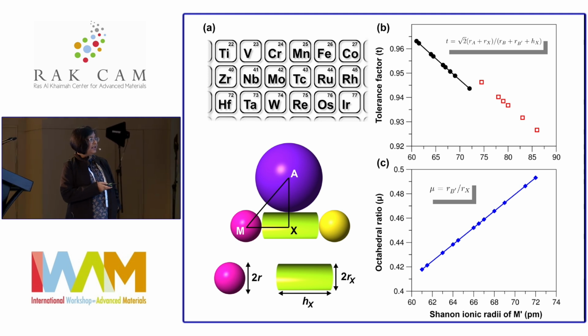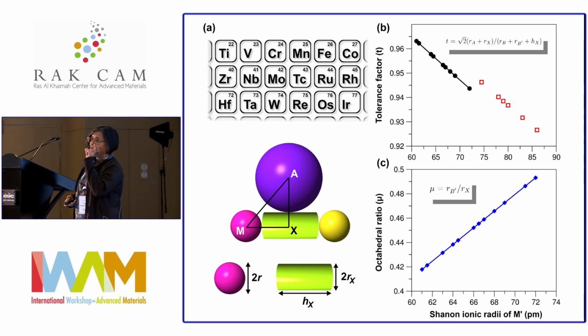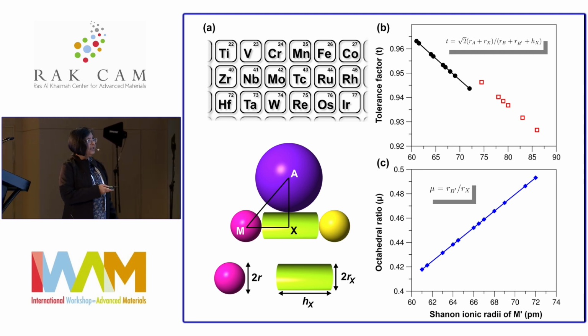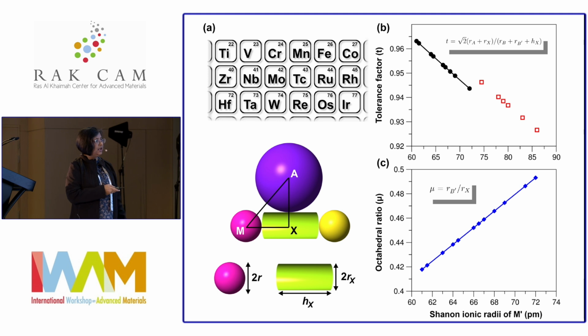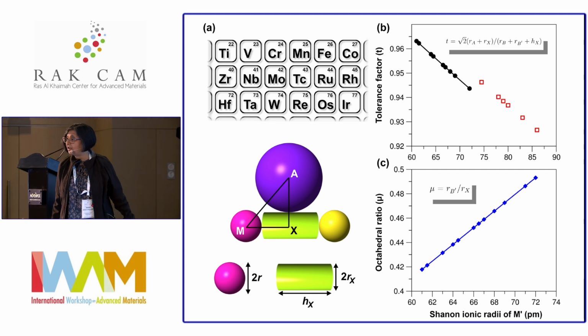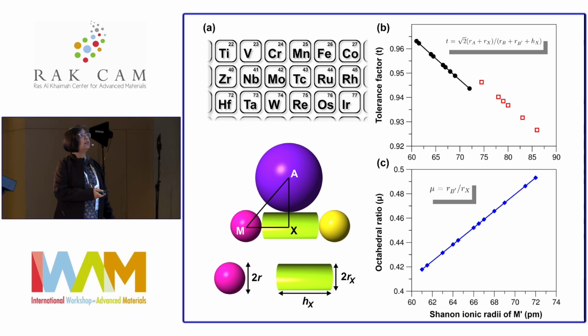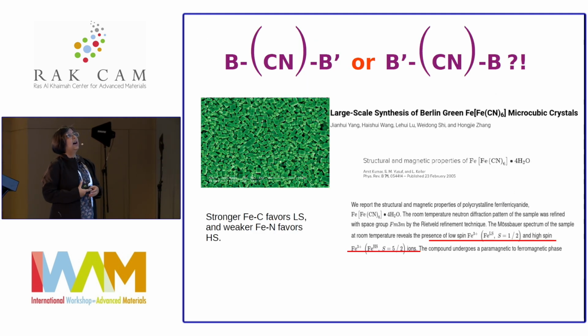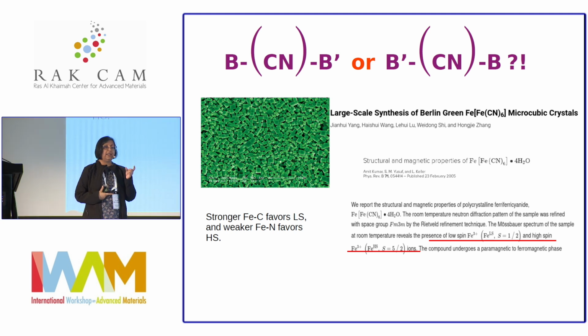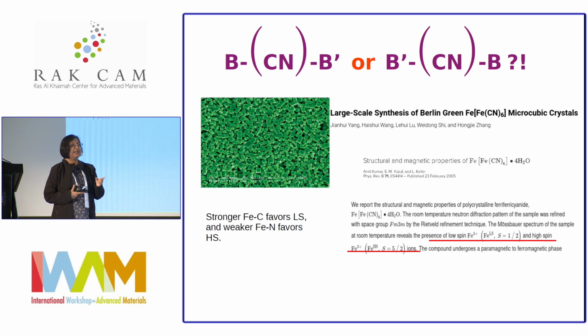So just as a side comment, since you are now considering the polyatomic ligand, which is like a cylinder, when you are calculating the tolerance factor, that's really not the normal way, because you have to introduce the height of it and also the radius of it. And Tony actually worked out all in great detail. So thanks to all this work, we could calculate that. Now, there are two possibilities for which way this CN bond will be. Will it be linked the C to B and N to B prime, or the opposite? In fact, both are possible. So a priori, you have no idea how they will be basically linked.